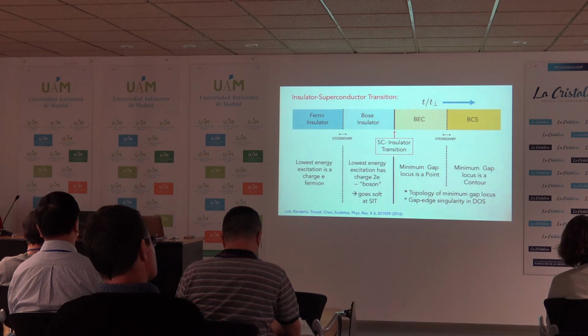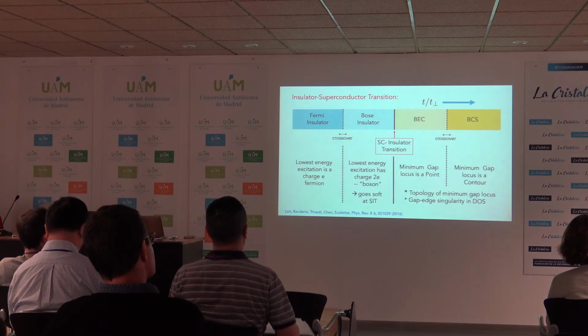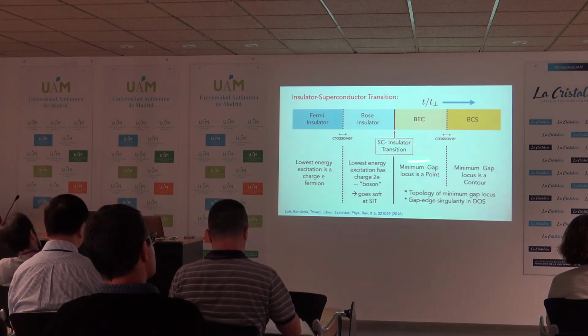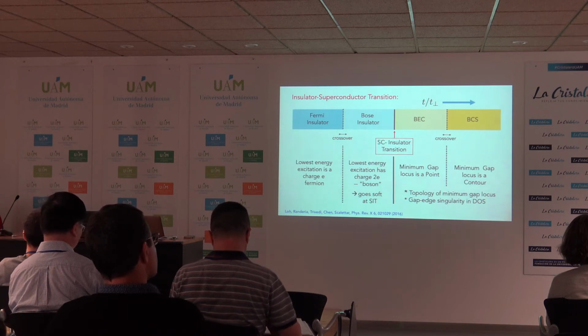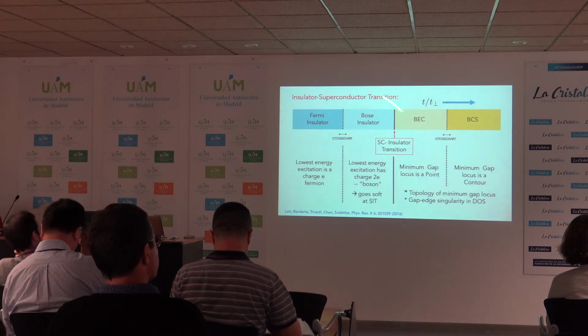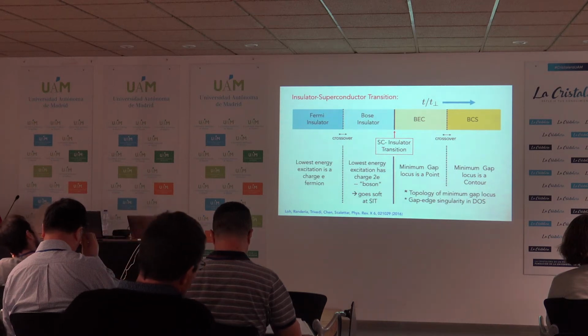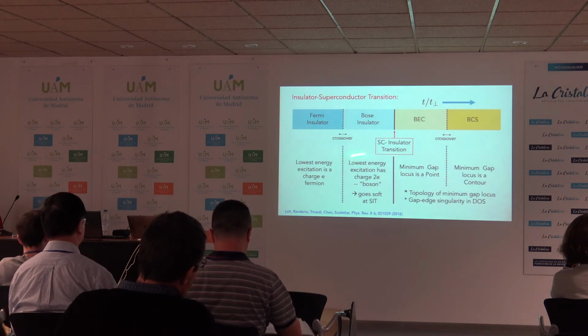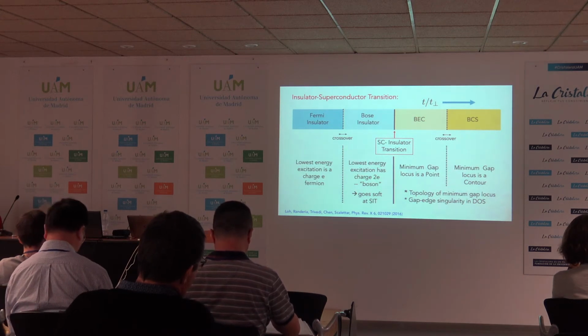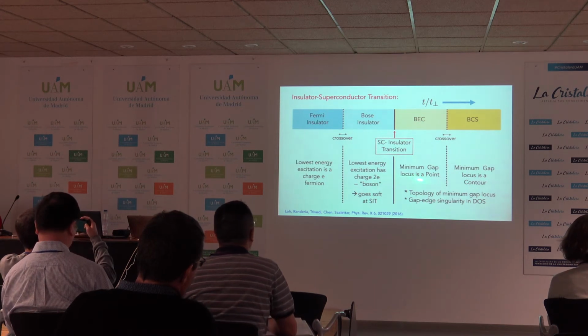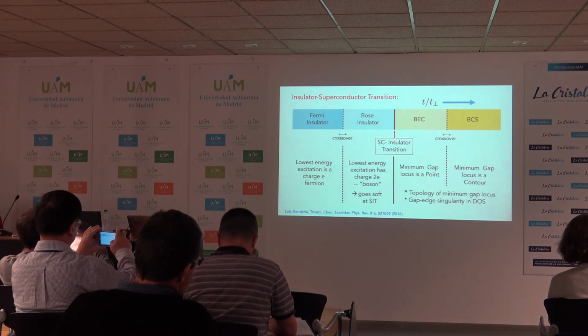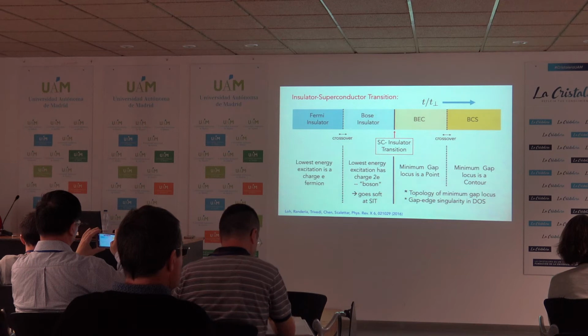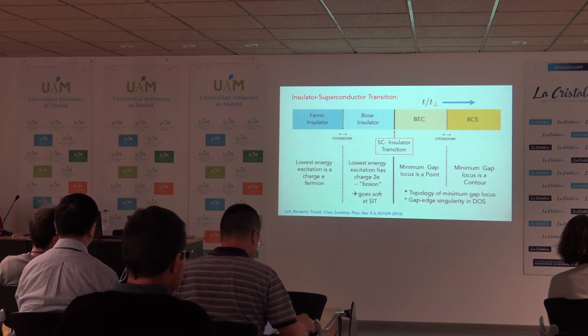Okay, so that's part one, and here's a summary. Anytime you see a superconductor to insulator transition, my message is look close to the transition. Neither the insulator nor the superconductor is going to be your average type. The insulator will already have signatures of pairing, in that the lowest excitation should have charge 2e, should be bosonic. And even on the BEC side, if you can do ARPES or tunneling, you should see either a minimum gap locus at the gamma point or a step-like density of states.